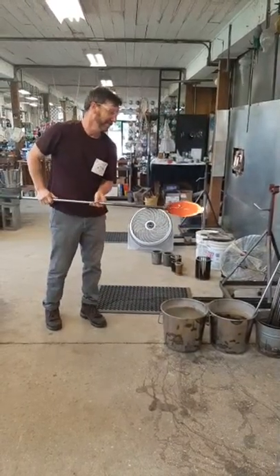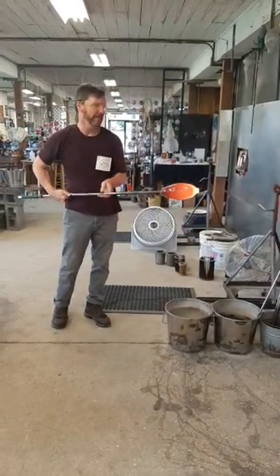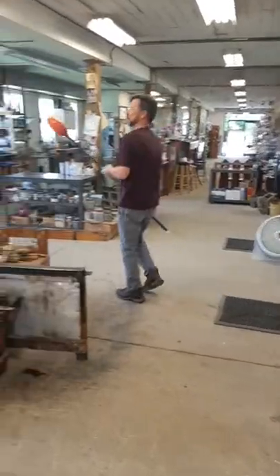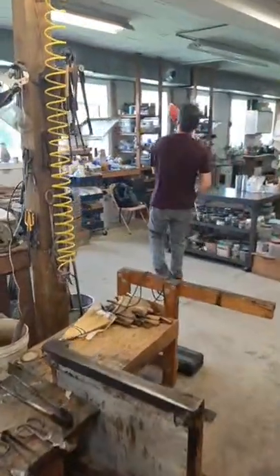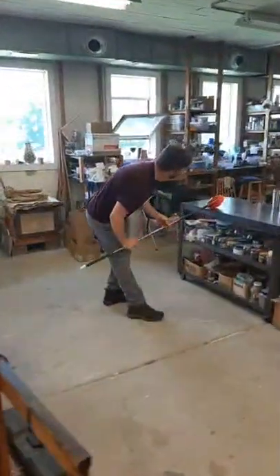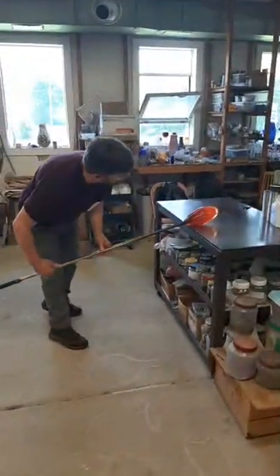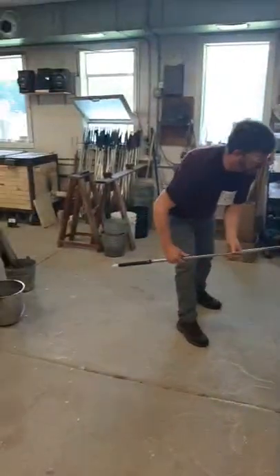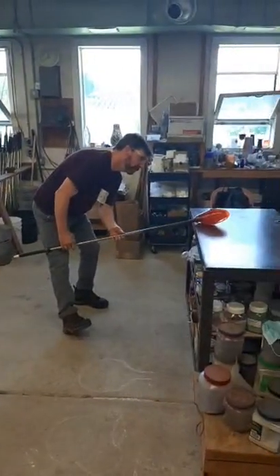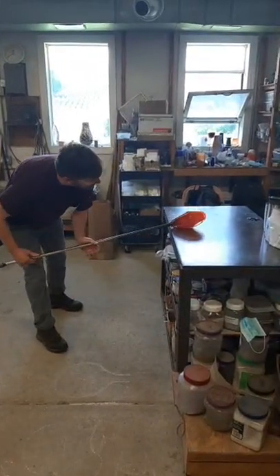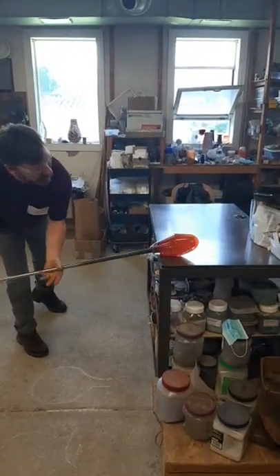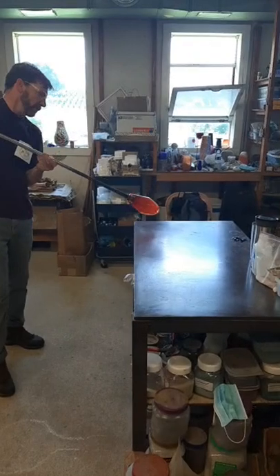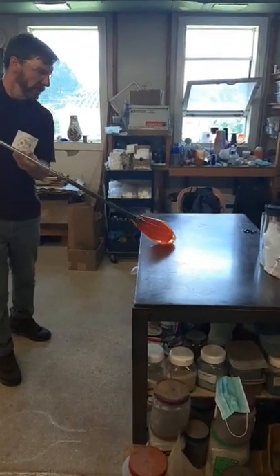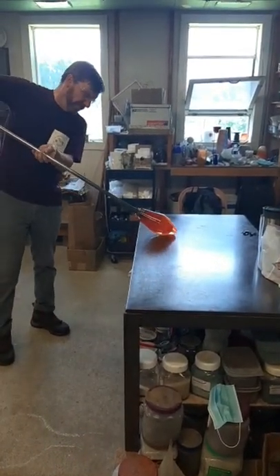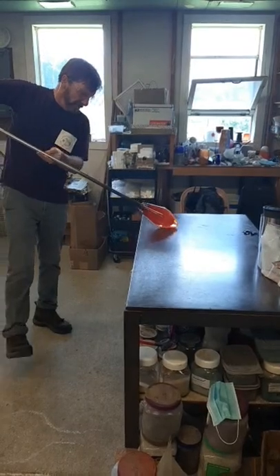Pivot to level and keep turning, and the string of glass just burns itself right off. It gets so much thinner, and it's still so hot that it just burns apart. Marvering with the iron down low like that pushes the glass off the pipe. Notice he's cooling the glass that's within about the first 7 inches of the pipe. By inverting the angle, he cools the other end and shapes it.